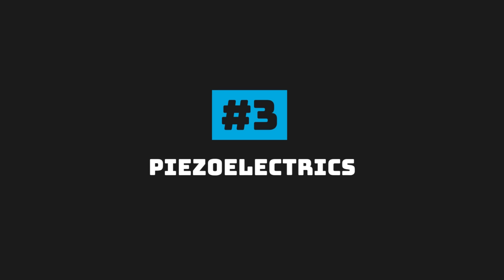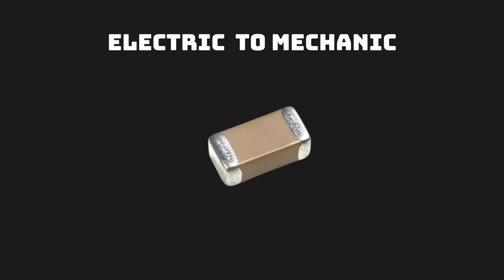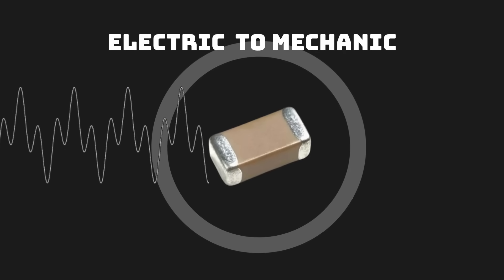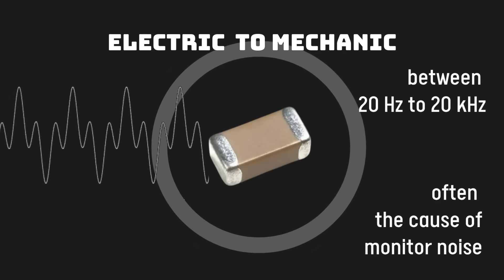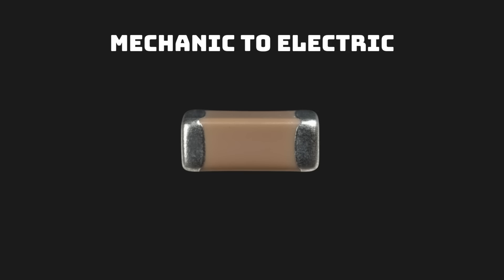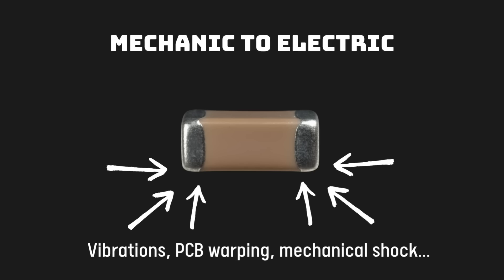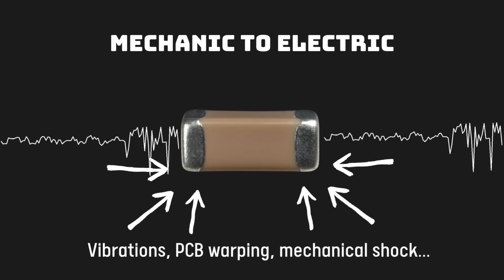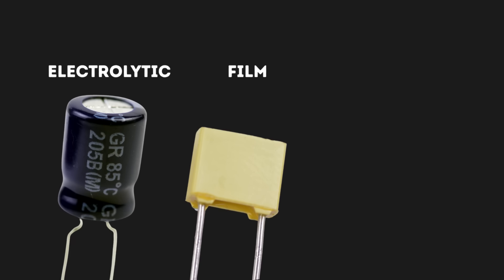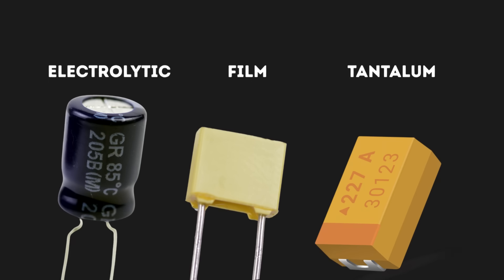Another curious effect is piezoelectrics. Just like resonating crystals, these ceramic materials change shape, expanding and contracting with an applied electric field. These changes create acoustic waves, which can be heard if the frequency of the oscillation is within the audible range. The opposite effect is also noticeable on low-noise circuits, especially amplifiers, where mechanical vibrations are translated into voltage noise. To avoid that, reduce the voltage ripple with other capacitor types or use class 1 capacitors in sensitive circuits.